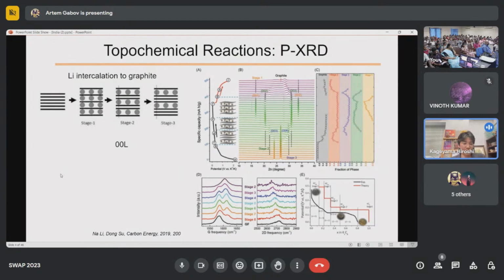So experimentally, what we probe such topochemical reactions with, the first thing is to perform powder X-ray diffraction. So this is from the review paper on graphite intercalations. You can see some staging behavior. The X-ray diffraction pattern changes in this way. So you can identify what intercalation is happening.